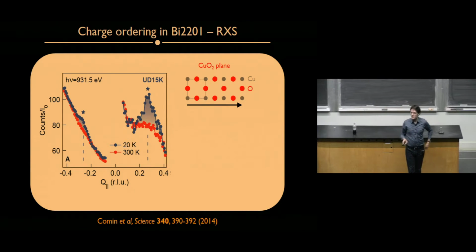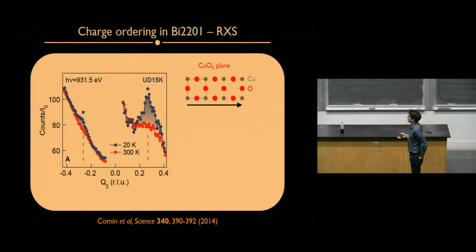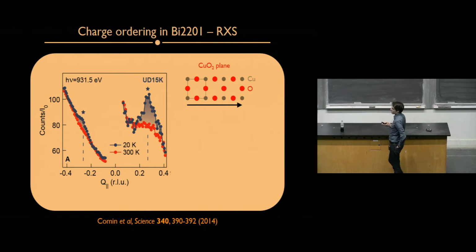We studied this in one of the few missing compounds, which was bismuth-2201, one of the bismuth-based cuprates. And we found charge order to be present there too, at a wave vector of 0.25 reciprocal lattice units, so with a periodicity of about 4 unit cells in real space.